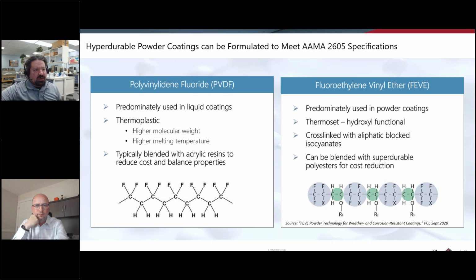Now, for traditional thermoset powder coatings, we have the fluoroethylene vinyl ether, or FEVE, and those are a lot more like a typical powder coating resin. The melt point is in line with what we're used to processing in the extruder, and the functionality is just like the hydroxyl functional polyesters. So they're cross-linked with the same sort of blocked isocyanates. The isocyanates are very weatherable, and so those don't hold you back as far as weatherability goes.